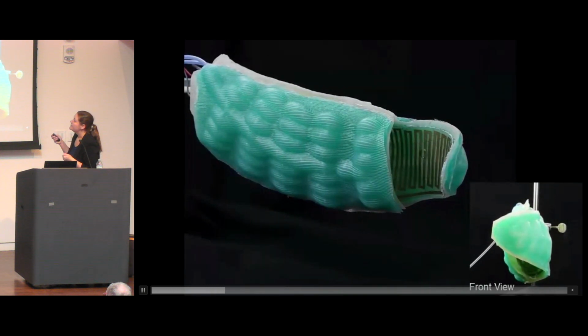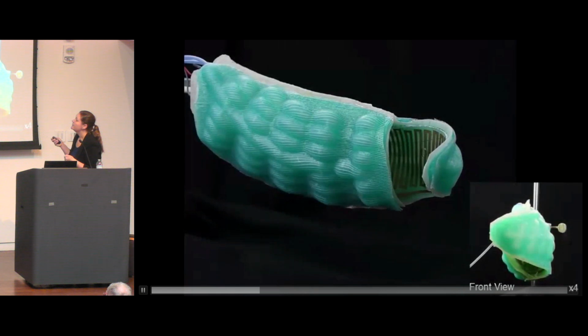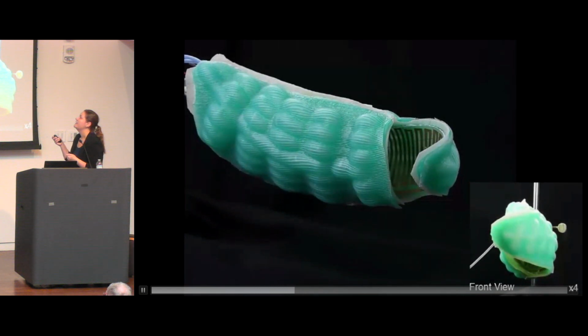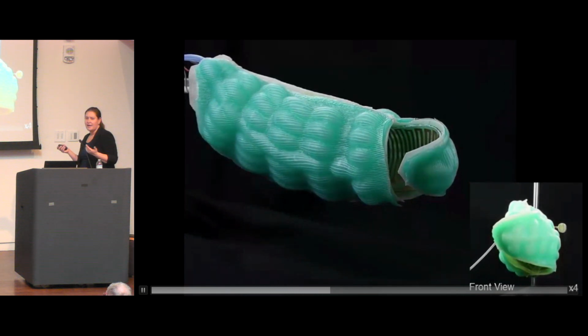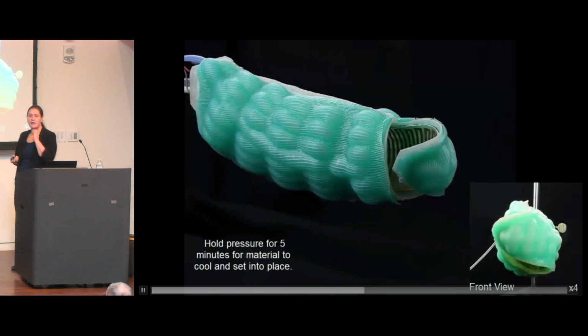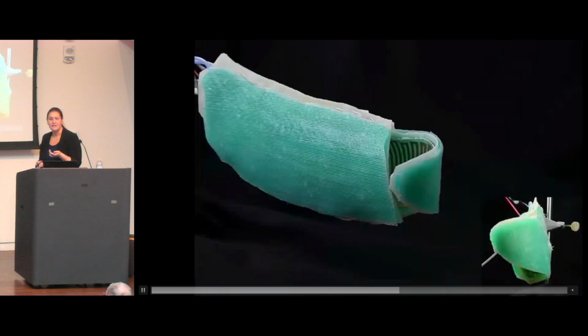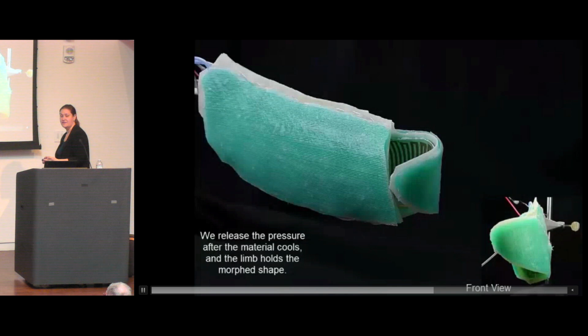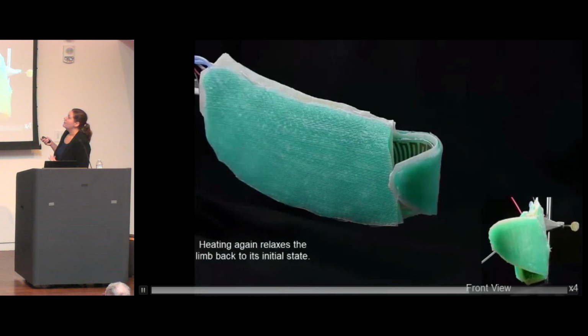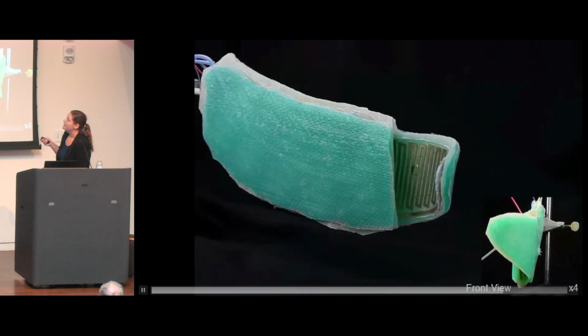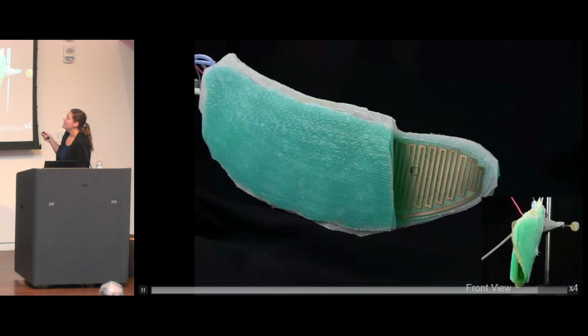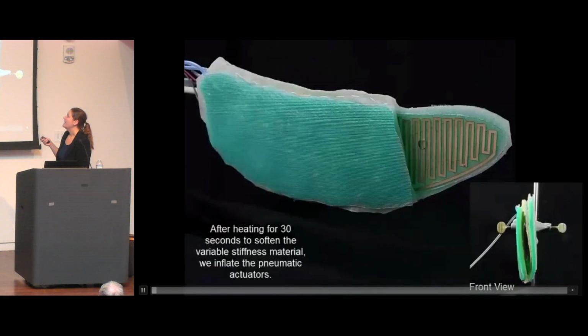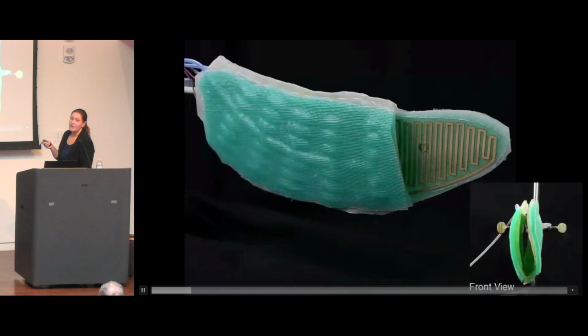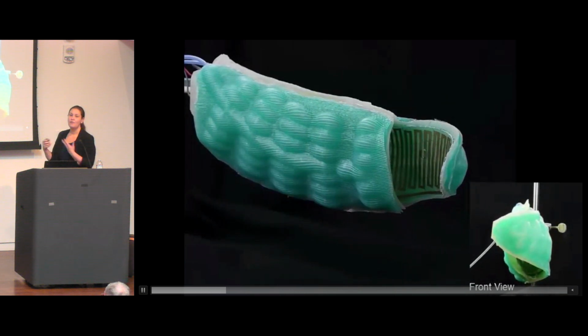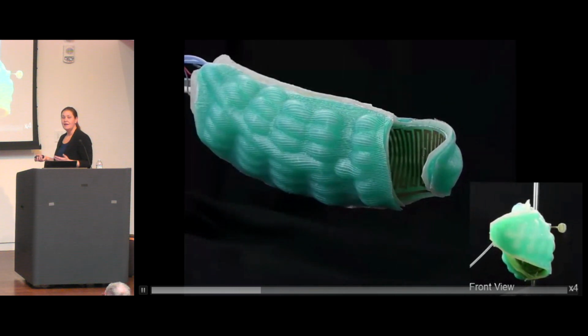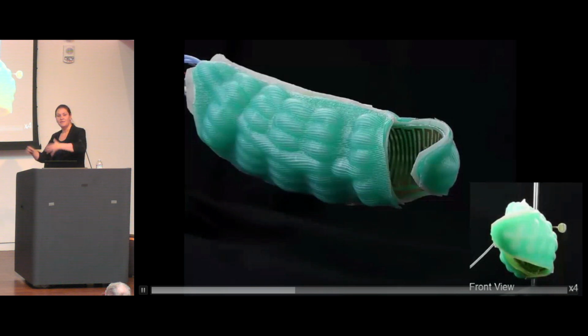And then we use a thermoset epoxy as our variable stiffness material. That's the clear material that you can see going into the limb here. It has a glass transition temperature, and its stiffness decreases by about an order of magnitude when we warm it above that glass transition temperature. And the way we warm it is using this co-located heater. So you can see a laser cut copper heater that's embedded within that thermoset epoxy. And so we simply apply current, joule heat the heater, it warms the epoxy, softens the limb, and then we can use our actuators in order to move it into the leg shape.